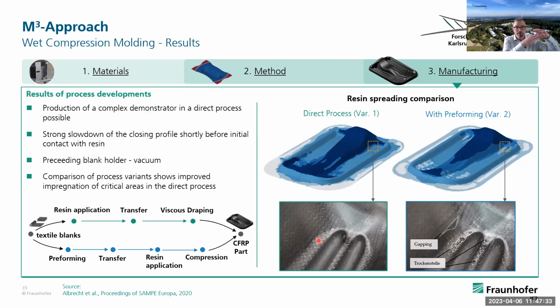So when the permeability is higher, it's rather better to have them impregnated properly, then squeezed out, rather than to have a preform where the permeability is not given anymore, and we have too high fiber loadings in those areas that prevent impregnation. So it was vividly demonstrated how a complex process could be systematically investigated, understood, and successfully transferred to manufacture a complex demonstrator using this M to the power of 3 approach. The advantages of the mutual interactions of mechanisms could be demonstrated here and validated, also with some literature comparisons.